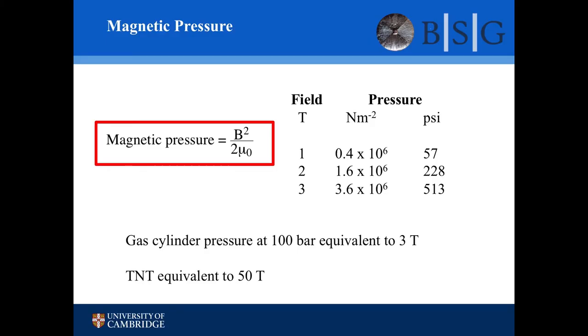Okay, so to put the field into context, the thing that we're interested in, magnetic pressure, goes as field squared. So the bigger you can go, there's an increasing return. Magnetic pressure and energy are both measured in the same units. If you can go to 3 tesla between 2 bulk superconductors, the pressure you'd get would be the pressure you'd experience in a gas cylinder. If you could go to 50 teslas, that would be an energy density equivalent to TNT.